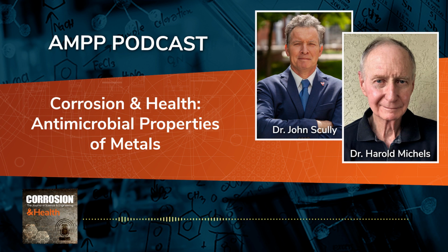The one thing about the silver that's really unknown is that in some of the applications, why should silver oxidize to form a silver cation? And so people have embarked on using silver nanoparticles, and nanoparticles will corrode faster than, let's say, a flat slab of material. And so you can get this nanoscale corrosion where you release silver 1+ that might occur from a nanoparticle, but might not occur from a large flat surface of silver.